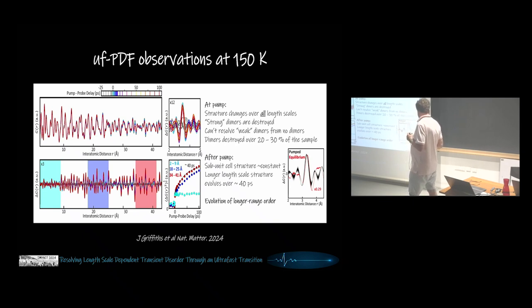Okay? And then we compared this differential, which is something I was supposed to mention before, obtained in this pump probe experiment, that's the black curve, with the signal that you obtain if you drive the transition by temperature. And it turns out you had to scale the temperature-driven response by basically 0.3 to get the same scale, which suggests that in our sample, about 30% of dimers are being removed.